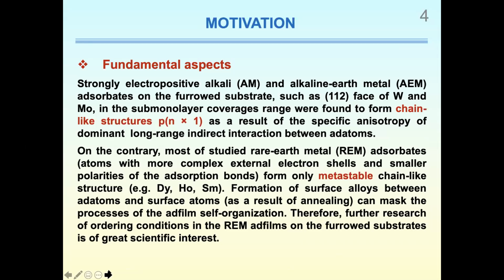However, in the case of adsorbates with more complex external electron shells and smaller polarities of the adsorption bonds, such as rare earth metals, such long-range indirect interaction through the electrons of the substrate apparently has a smaller effect on the structure of the film than the short-range interactions between the atoms. Indeed, among 5 studied rare earth metal systems, a stable linear chain-like structure with a long period has been observed only for ytterbium. For the gadolinium on molybdenum 112 system, chain-like structures were not detected at all.